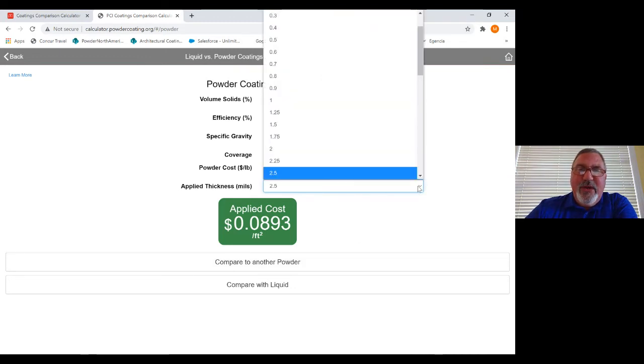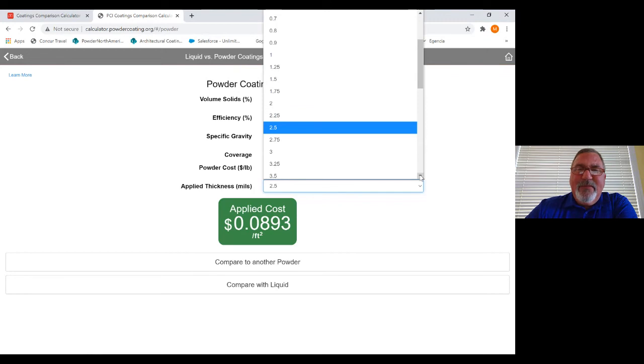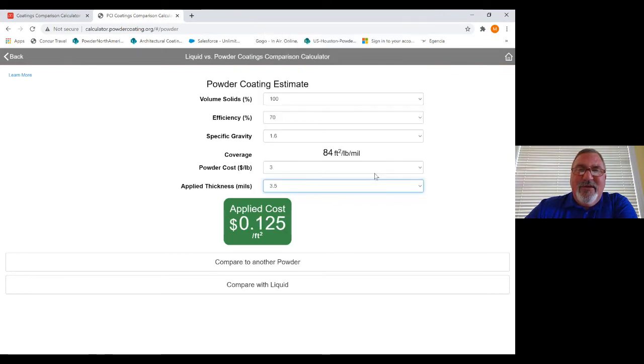So now let's just real quick jump down and say, well, what happens if we're putting 3.5 mils on? Now you can see the comparison. So we went from 8.93 cents per square foot to now 12 cents per square foot. Now that's a hidden cost, and I say it's hidden because you really are paying it, but it's not one that you see right up front, because if you're not measuring film builds and you're not controlling film builds, then it's just presumed that if you quote a job at 2.5 mils, you're going to put 2.5 mils on. And so that was a pretty big difference there.